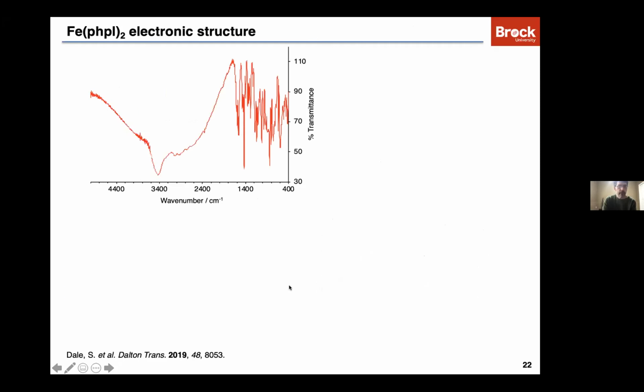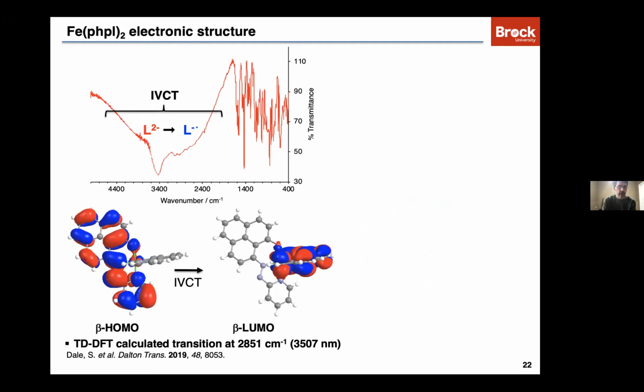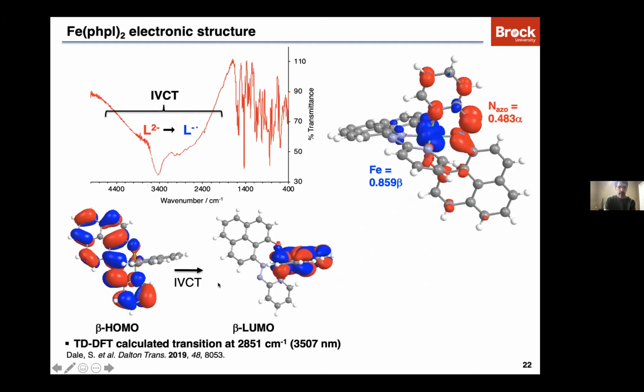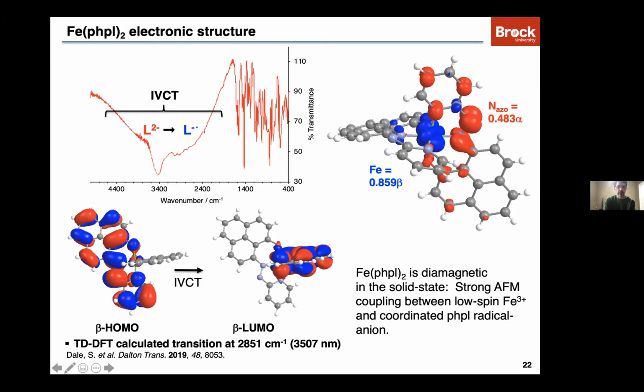Now, if we look at the IR spectrum, you see this very, very intense and broad feature centered at around 3,200 wave numbers. Now, we've calculated the electronic structure of this system, and this happens to be an IVCT band. So an intervalence charge transfer transition from the ligand dianion to the ligand anion radical. And in this system, we have low spin iron 3+, and the complex is completely diamagnetic. So there is no spin transition or anything of the sort, low spin iron 3+.